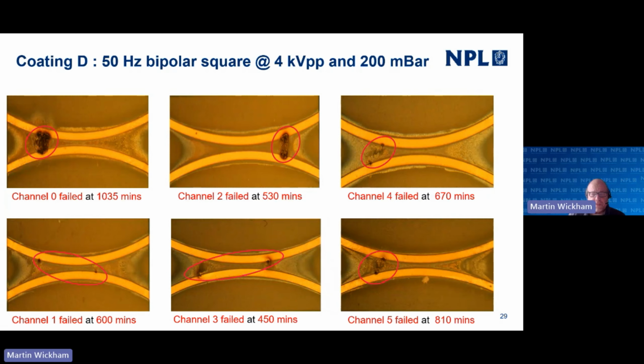Again, similar sorts of failures, depending on how soon before. We are putting these halos down to delamination of the coating from the surface. So there's something happening potentially in terms of adhesion of the coating whilst we're going through this electrical fatigue test.